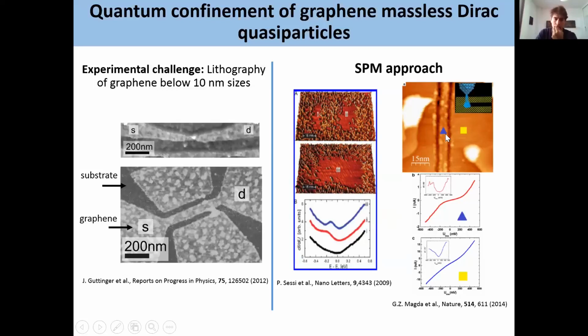Another effort is here in this work that I'm showing, where they claim to cut graphene using the STM tip. They do it with high humidity, and they pass a bias, a tunneling current, and they are able to cut graphene. And they measure spectroscopy inside and outside, and they report the existence of gaps. But if you look at the spectra, there are faint gaps. I mean, there is a decrease in the conductance, but it's not that the conductance goes really to zero.